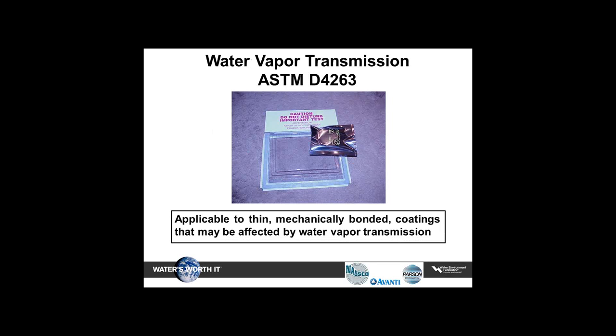There are such things as water vapor transmission through the wall of the manhole, as per ASTM D4263, and it's usually applicable to thin, mechanically bonded coatings that may be affected by water vapor transmission through the wall. In other words, if there's water coming through the wall, and we can test for those things, then over time it will tend to disbond the coating, and it will begin to peel off. And once it begins to peel off, of course it'll totally fail over a matter of time.